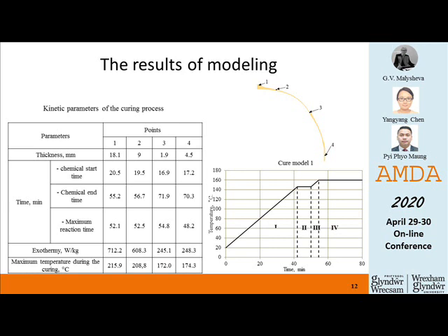The results showed that the maximum amount of heat is released at point 1, the minimal at point 3. So the temperature field along the bottom control varies nonlinearly. The temperature decreases from point 4 to point 3, then the temperature on the surface of the part increases from point 3 to point 1. With an increase in the thickness of the structure due to the concentration of the heat flow, the maximum temperature and the release of heat increases.